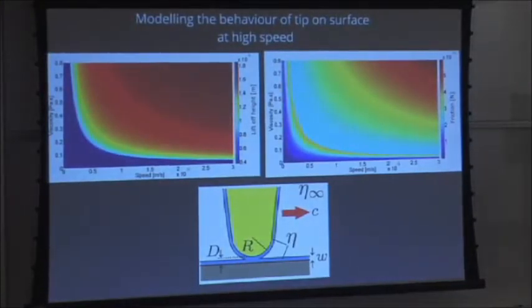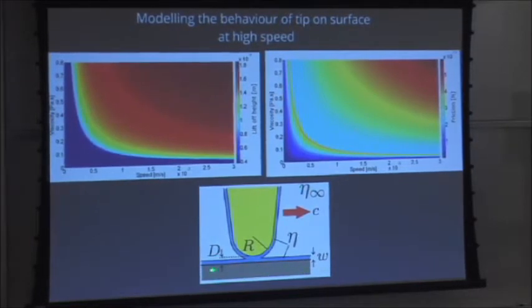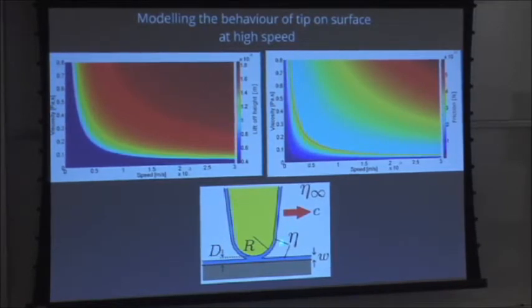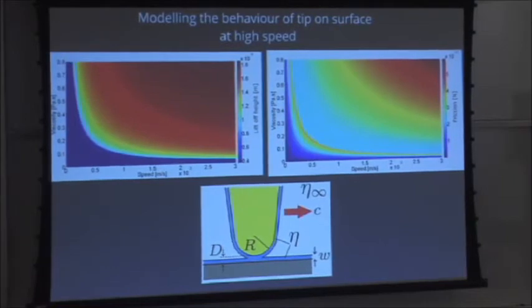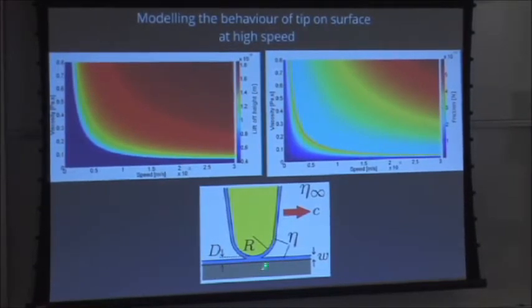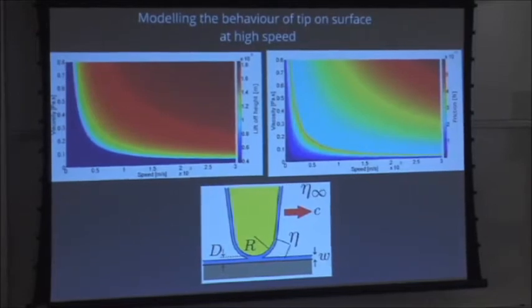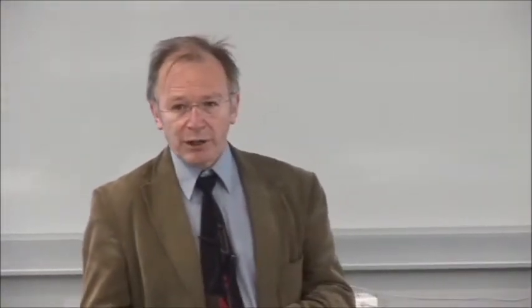Here are some calculations. Here's our tip, here's our surface, here's a water layer. Now this could be air, or it could simply be that water layer and the water layer on the tip. There's always tens of nanometers of water on things under ambient conditions. But it could also be the bulk water, because near the surface the water is ordered, and it has different mechanical properties, much higher viscosity and much higher elasticity than the water in the bulk. So we have two viscosities, one for the bulk and one for the water near the surface. Taking that, which is not really an assumption because we've measured it, we can build models, and here are different models if we change the viscosity.